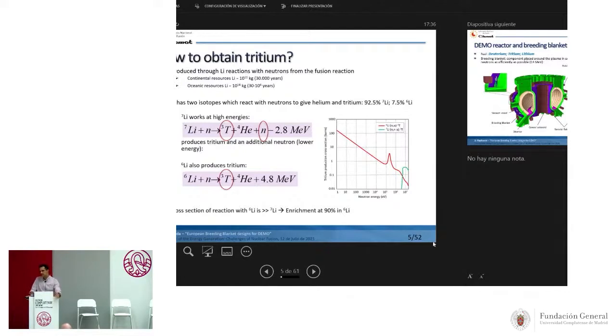And lithium-6 also produces tritium, and what is interesting here is that the cross-section of lithium-6 is really large. It's large at low energies, so this is good. But the problem, as I mentioned, is that naturally we find lithium-7. So we need some enrichment in lithium-6 of this fuel.